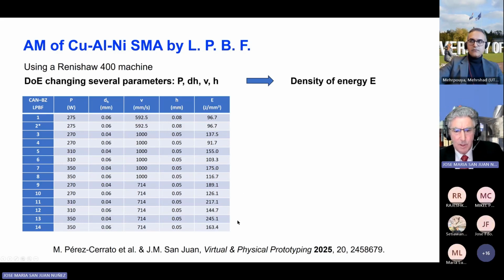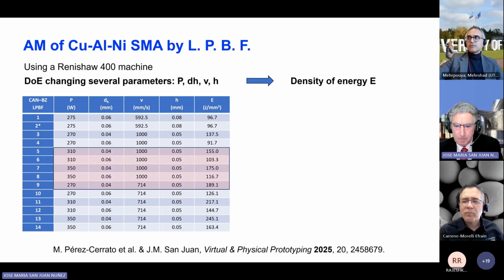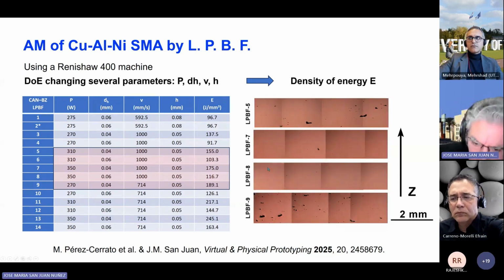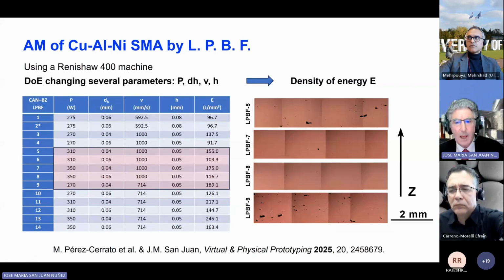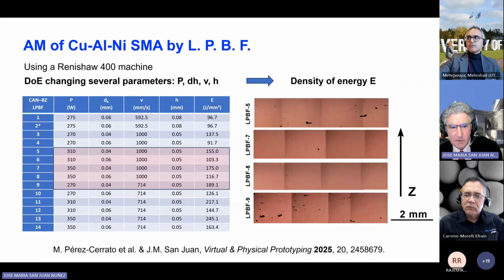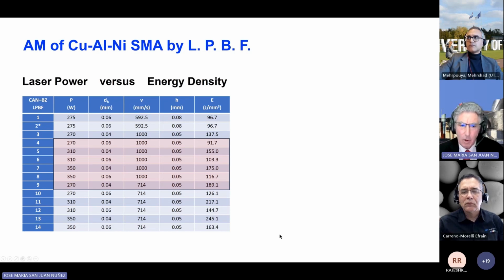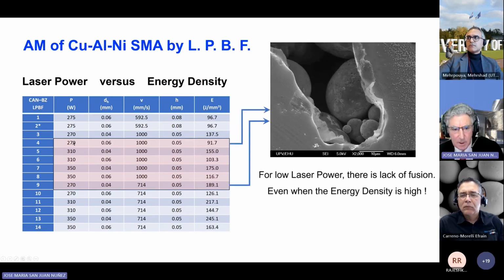And then let me focus on the central part of this DOE. Sorry. This is the aspect we get by optical microscope. So when we have low power in this 5 or in this 9, here and here, we have pores very, very big, and this is improved in the case of 8, in which we have practically no pores. This is because for low powers, here and here, for instance, there is a lack of fusion. Okay, and you can get powder particles not melted in the cavities of the big pores that you find in